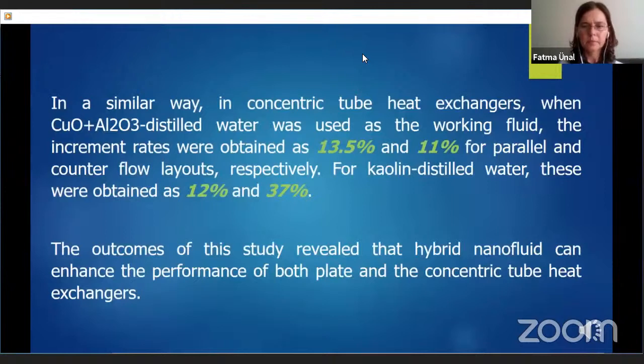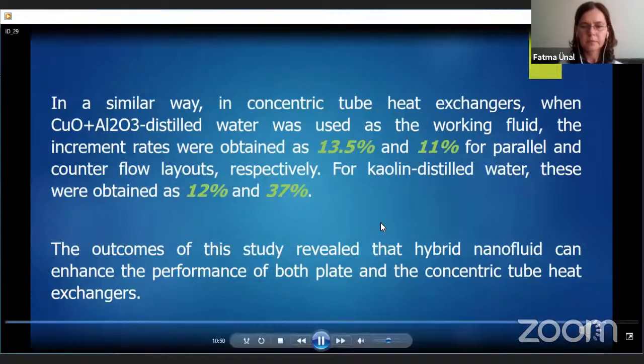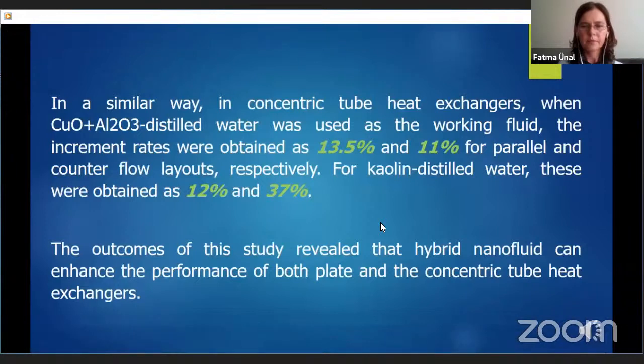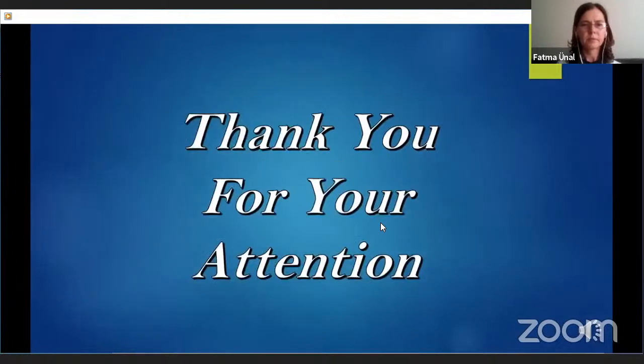Similarly, in concentric tube heat exchangers, when hybrid nanofluid was used as a working fluid, the increment rates were obtained as 13.5% and 11% for parallel and counterflow layouts respectively. For kaolin distilled water, these values were obtained as 12 and 37%. The outcomes of this study revealed that hybrid nanofluid can enhance the performance of both plate and concentric tube heat exchangers. Thank you for your attention.